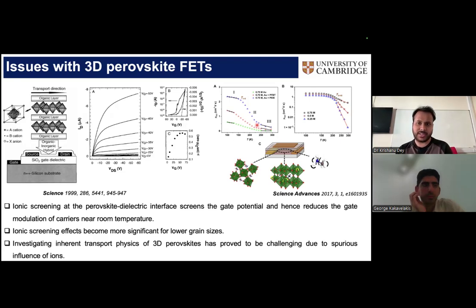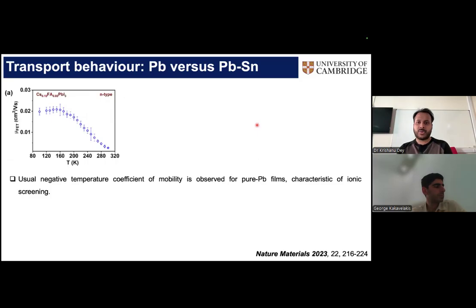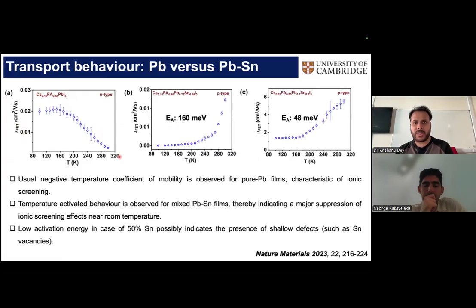So I wanted to see whether this effect is still predominant in the tin-containing perovskite devices. We did the same measurements starting with pure lead, and you can see that for pure lead we see a very similar trend. The mobility measured from the FET goes down as a function of temperature, and this is a characteristic of ionic screening behavior. But as soon as you introduce tin in there, you again completely change the behavior. You now see a positive temperature coefficient, or an activated behavior.